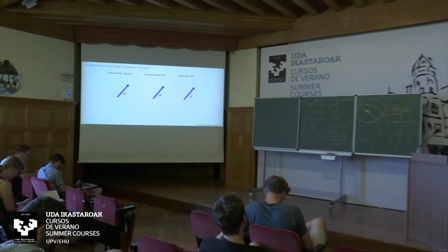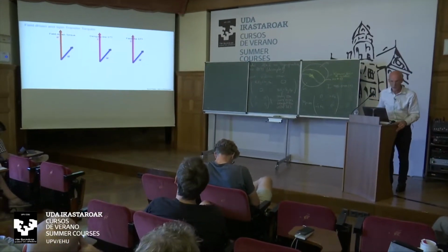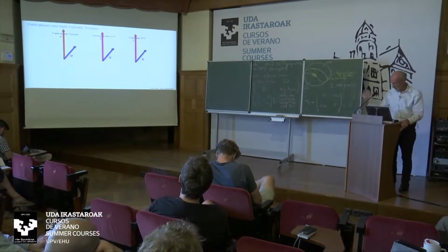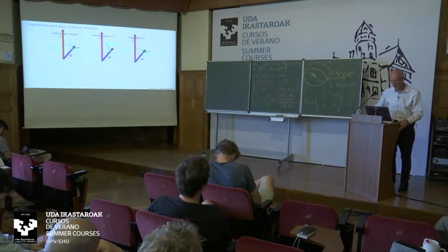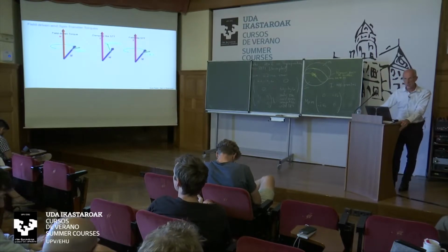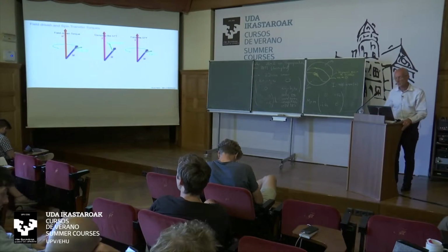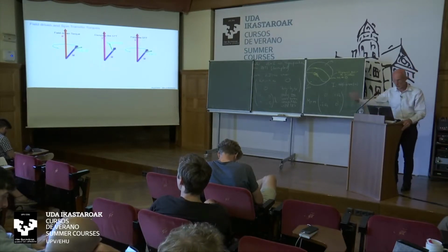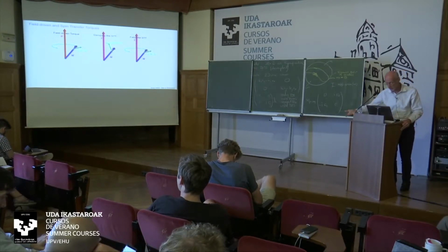And then we end up with, in the first case, let's say, a magnetic field. As you know, the magnetization will precess around the magnetic field because of the Lorentz force, M cross H. And this will continue to precess indefinitely unless there is some damping, some loss of angular momentum. This is what always happens in magnetic systems. There will be some damping, some loss of angular momentum to the lattice through spin-orbit coupling, typical Gilbert damping.